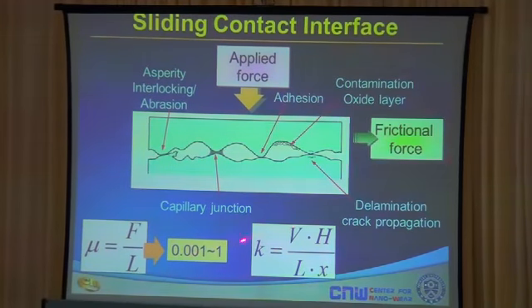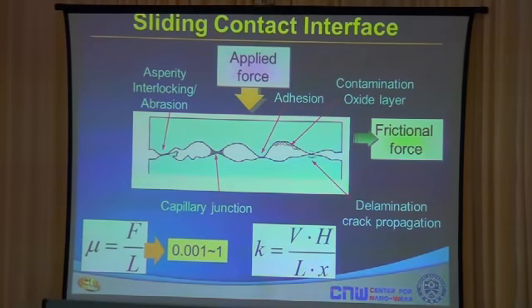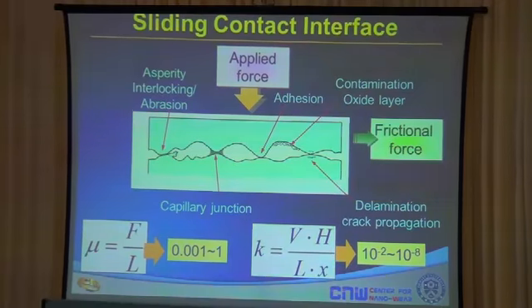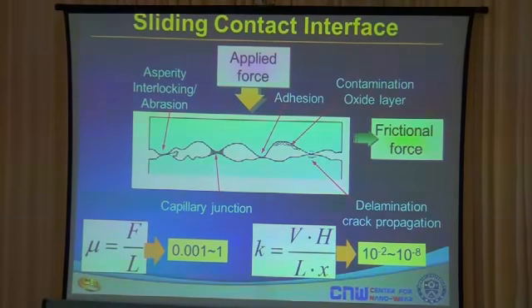In tribology, what we're trying to do is to first be able to predict what the friction coefficient is, which is in the range about 0.001 for a very well lubricated system, and can be as high as 1 or above for dry systems. And for wear coefficients, it can be about 10 to the minus 2 to 10 to the minus 8, depending on the system. Very wide range.